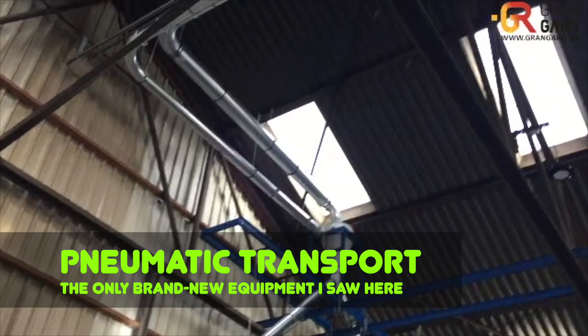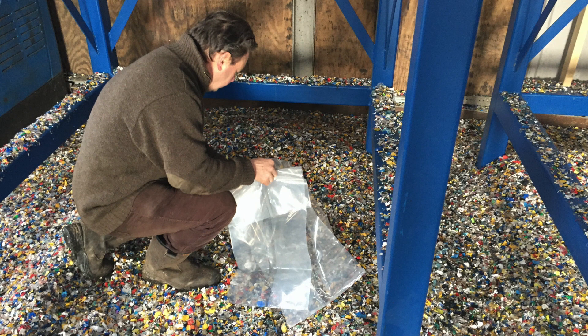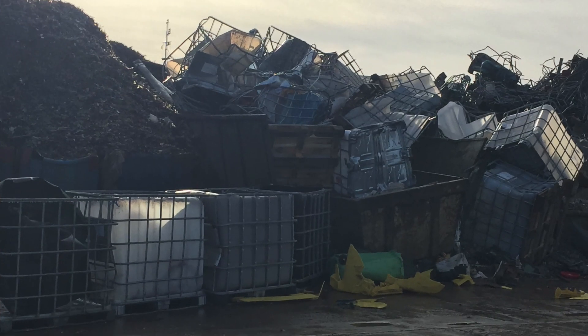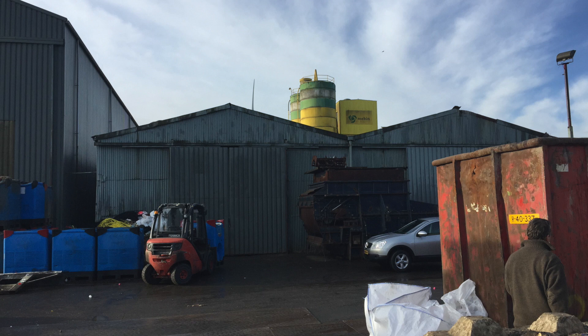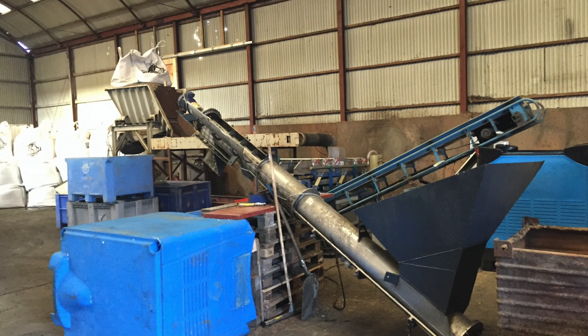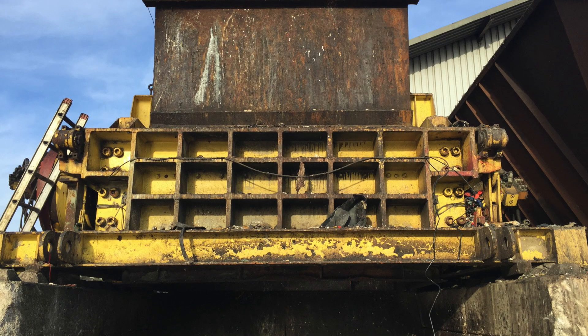The moisture of the output is still high, more than 10%. The percent of impurities such as LDPE, PP and PET is also still high, up to 20%. But there is already demand for such a product. There are all sorts of containers which are partially resold after manual washing and partially crushed and included in the mixed colored HDPE. They process up to 100 tons monthly of automotive fuel tanks — these are black large pieces after shredding on a two-shaft shredder. They don't wash it, but sell it as-is.